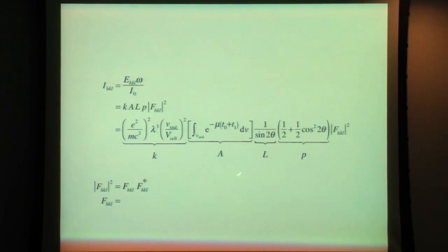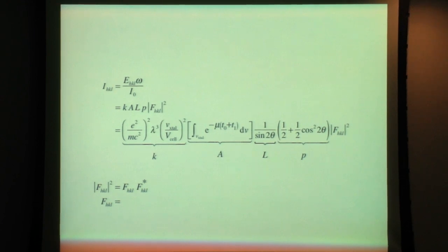Because the reciprocal lattice point also has a volume, in the sense that surrounding the peak of the intensity in the scattered beam, there is some background and so on. So we don't have a reciprocal lattice point, we have a reciprocal lattice volume, a little tiny volume.